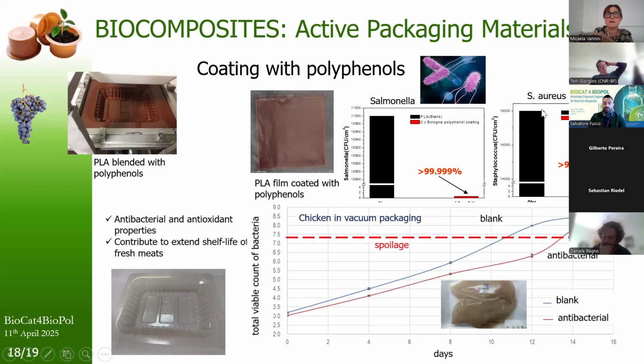Even when we applied the polyphenols as coating on an absorbent pad put in contact with fresh chicken, we observed a delay in the onset of spoilage by 3 days, demonstrating that the simple incorporation of polyphenols as filler confers antioxidant functionality to the entire material.